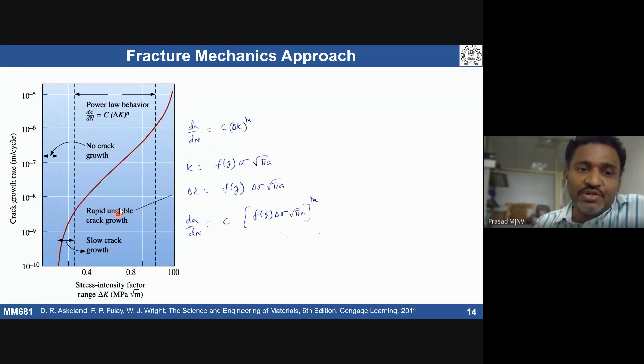So initially we do see slow crack growth, followed by an almost power law kind of thing. Then again we do see rapid crack growth taking place. So the higher the stress intensity factor range, the higher the crack growth rate. If the stress intensity factor is very small, the crack growth is going to be very slow. So an important regime for understanding fatigue behavior of material, people do establish this power law behavior.